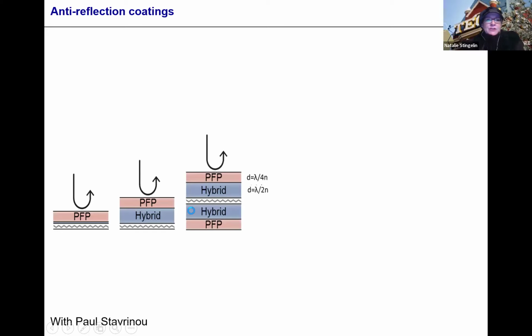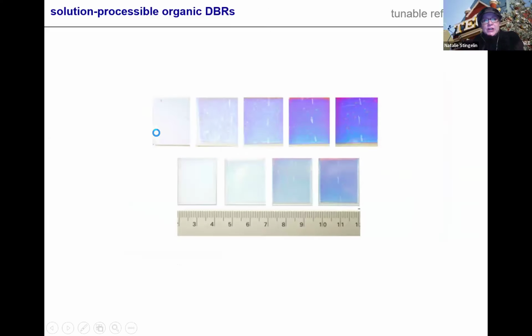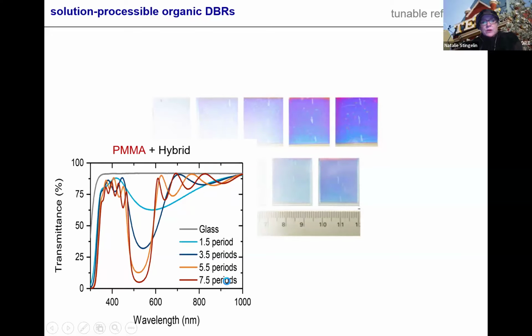What I can say is we used these types of anti-reflection coatings as well as the mirrors that come in the next slides here. And these were the big mirrors, as I showed with the Imperial College Tower reflection. We put them into the Saudi desert. So these were multi-layer structures. I don't know anymore how many periods they had, so how many layers. But the mirror survived 3 months in the desert without degradation. So there was no yellowing, etc. Clearly, did the fluorinated polymer lose some of their fluorines? I have no clue, though I would have assumed you would get yellowing eventually because you create a double bond at the backbone. So in short, we don't have anything quantitatively, but qualitatively, it seems at least the stack is pretty stable.